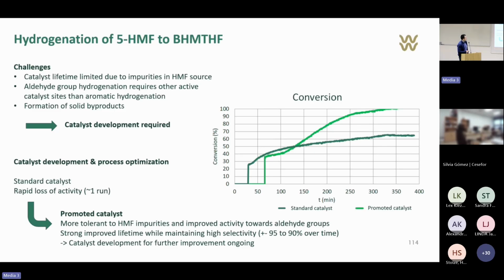And in the end, at the end of the project right now, we have developed a catalyst which is able to do multiple cycles of hydrogenation. So we have a strongly improved lifetime while also maintaining a high selectivity. In the first run, we have about 95%. It drops to 90% over time, but it's still quite high compared to the standard catalyst, which after run 1 is already deactivated. So that's basically a strategy, but the catalyst development definitely needs further improvement as well, and it's still ongoing.